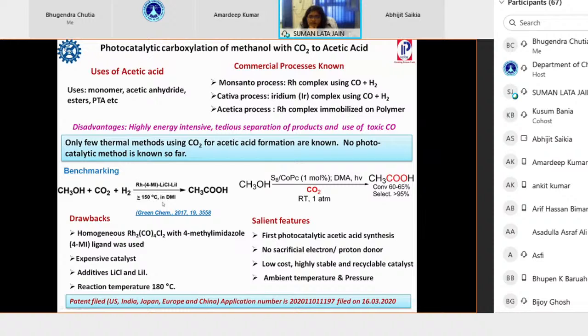This is our benchmark. This is the thermal method where a rhodium based complex has been used for the conversion of methanol, carbon dioxide and hydrogen to acetic acid at higher temperature. So a homogeneous complex was used, an expensive catalyst was used, a higher reaction temperature is used, and moderate conversion, like 60 to 70% with 80% selectivity, is reported. So with these drawbacks, we started our work on the photocatalytic conversion of methanol to acetic acid with various